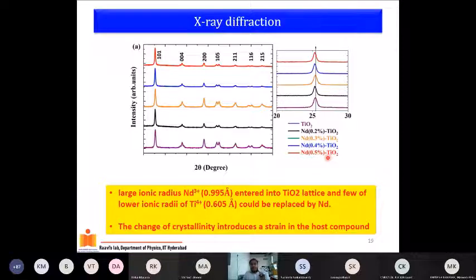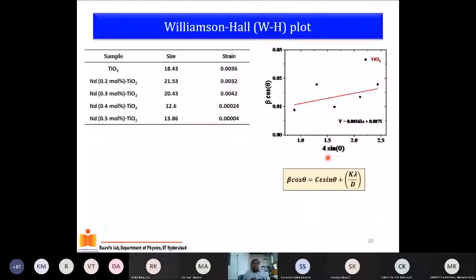So one of the simplest points you should remember is, as soon as you make a material, get the XRD pattern checked to make sure whether your material is what you expect it to be. Then you can use the so-called Williamson-Hall plot. Any paper or book or literature which talks about XRD will tell you how to use this plot to characterize your size and strain.